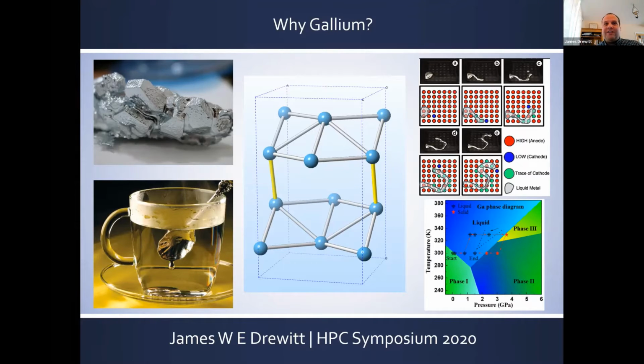Consequently, it's got one of the largest liquid stability ranges of any element, and also has an unusual 3% volume expansion on solidification. So the uses of some low melting point gallium-based liquid metals can have applications from cooling integrated electronics to manufacturing flexible and reconfigurable electronic devices.